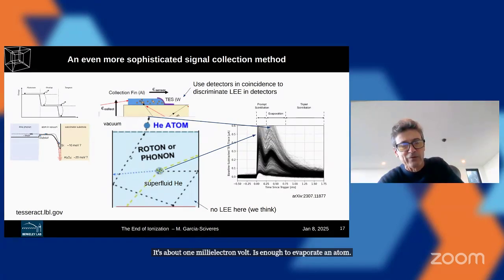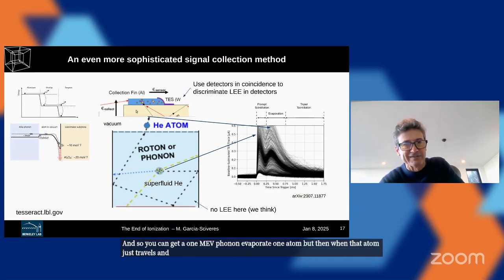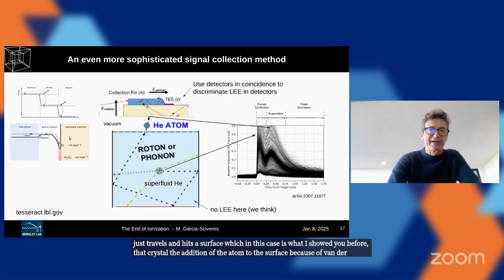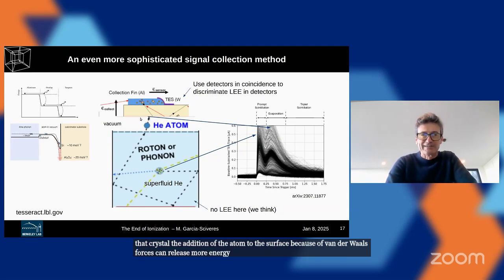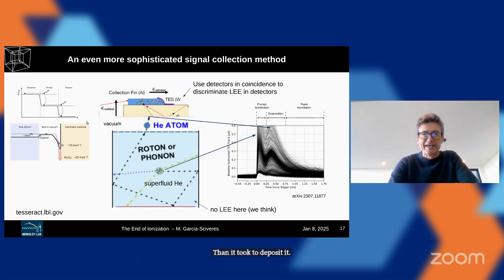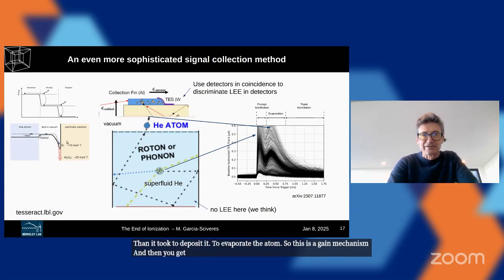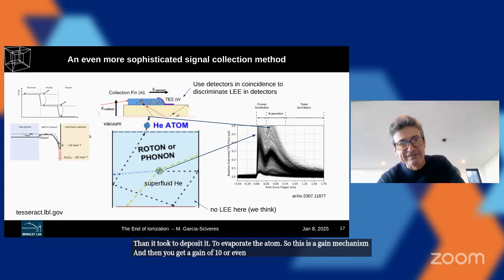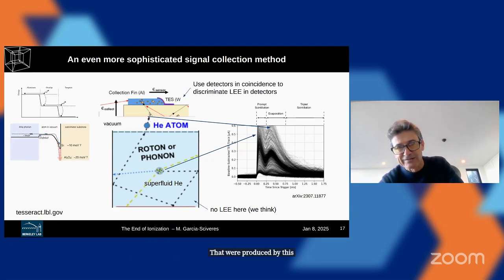And so you can get a 1 meV phonon, evaporate one atom, but then when that atom just travels and hits a surface, which in this case is what I showed you before, a crystal, the adhesion of the atom to the surface because of van der Waals forces can release more energy than it took to evaporate the atom. So this is a gain mechanism. And then you get a gain of 10 or even 20. And then you detect the phonons that were produced by this collision of this atom with this crystal.